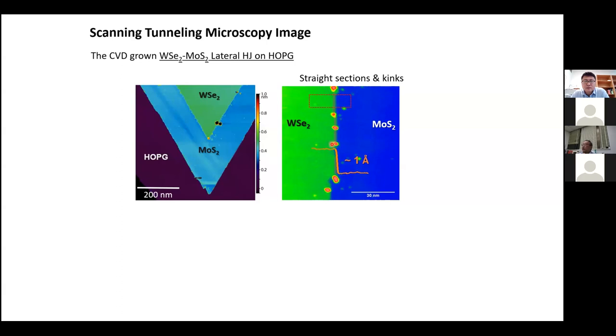So you can see quite a few straight sections, but here we constantly see this tiny little adsorbate right there. And our understanding at that time was that this is just some kind of adsorbate we couldn't get rid of, because this is a CVD sample, and you take it in UHV and some adsorbate still remains. And I probably don't have time to describe this, but this is tensile, that's where the misfit dislocation is. And misfit dislocation is closer to metallic, and that's where the adsorbate is.